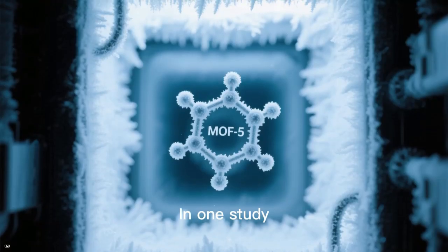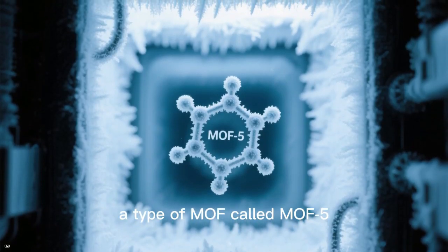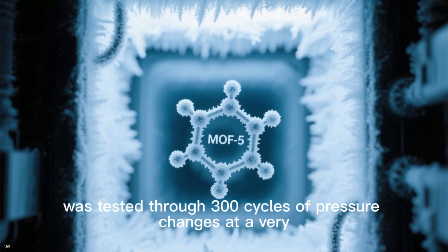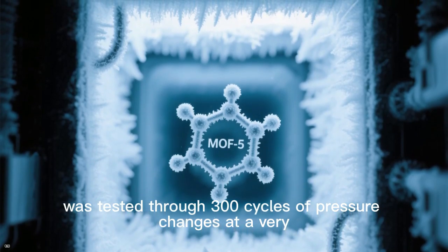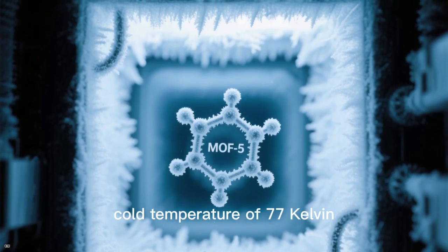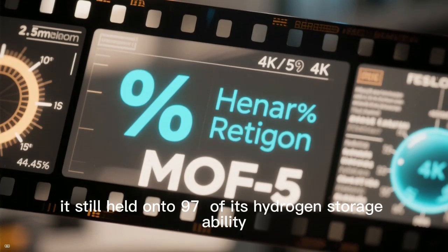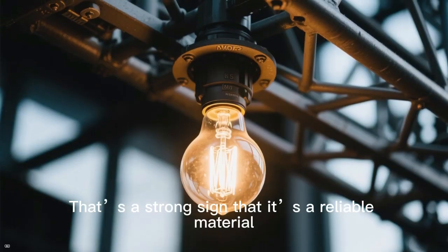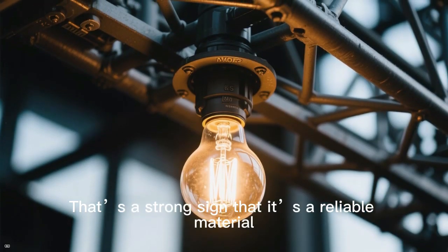In one study, a type of MOF called MOF-5 was tested through 300 cycles of pressure changes at a very cold temperature of 77 Kelvin. Even after all that, it still held on to 97% of its hydrogen storage ability. That's a strong sign that it's a reliable material.